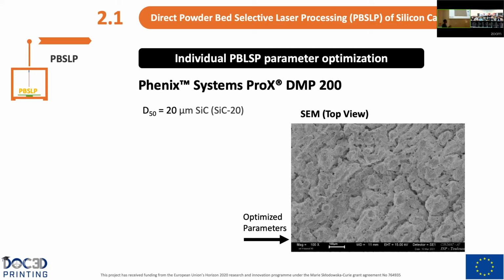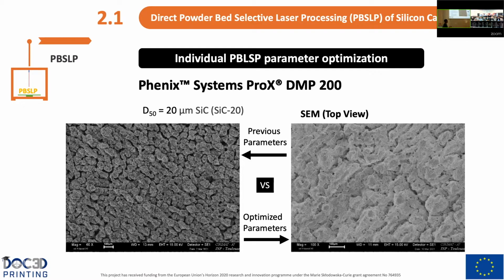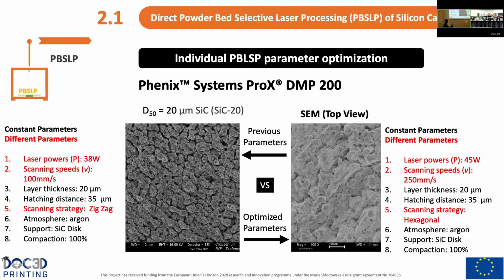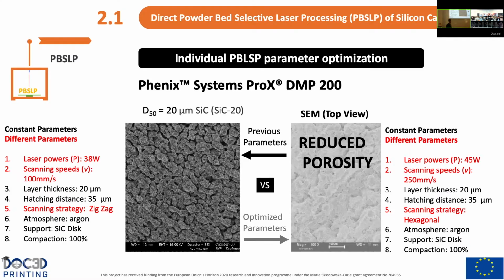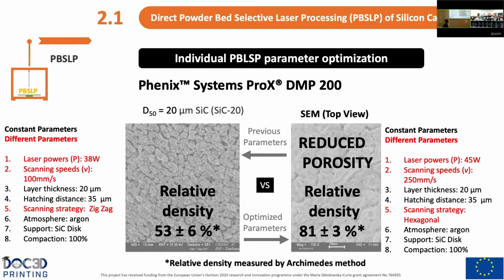But if we compare these optimized parameters with our previous parameters, in detail, laser power 38 instead of 45, scanning speed of 100 instead of 250, and zigzag strategy instead of hexagonal, we can observe, of course, that here we have a reduced porosity. And in numerical values of density, here we are obtaining 53% of relative density versus 81% of relative density.